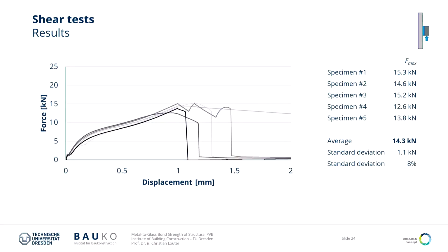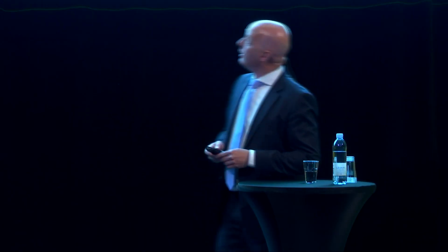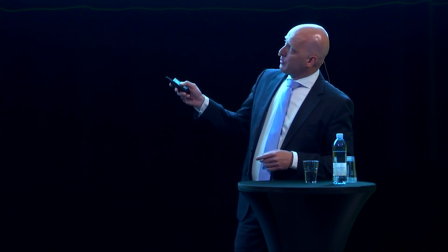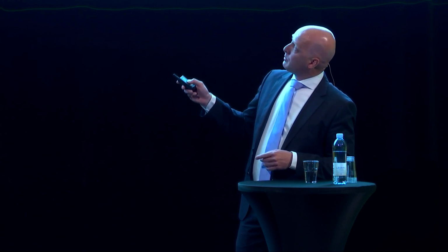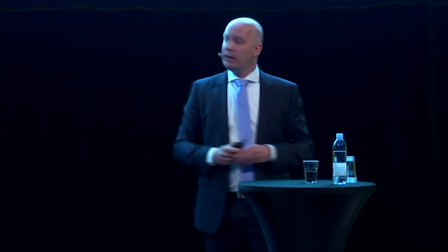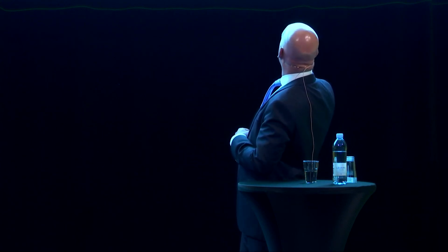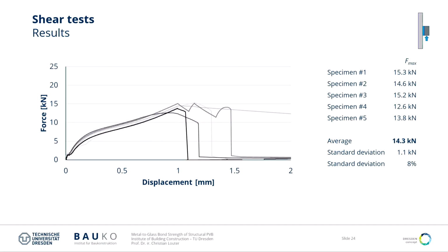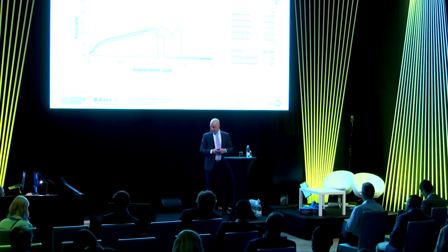These are the results. So again, the force, and then the displacement of the button relative to the glass. This has some initial settlement of the test setup, so you can ignore that, but you can see that it's quite consistent again. We reach an average failure load of about 14.3 kilonewton. A little bit higher scatter, let's say, but still an acceptable number there. So still quite consistent results. And in this case, we have tested 5 specimens. Still not a lot, but enough to get a first indication.